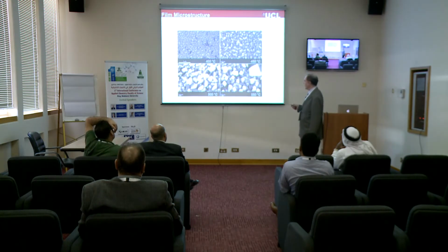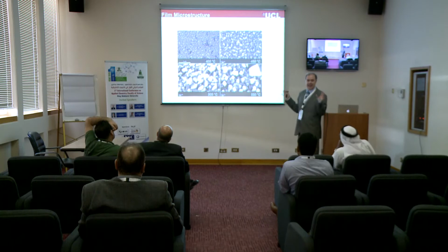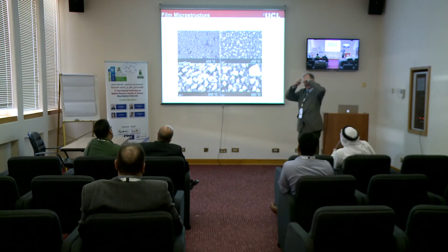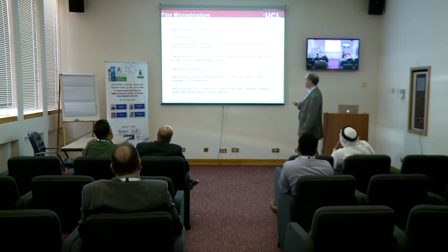When we do that, we produce very nicely crystalline doped tin dioxide films, and this is called a texture coefficient, which gives rise to how much preferred orientation you have in the film. When you look top down, this is what they look like. And they have this pyramidal microstructure. Now that's absolutely ideal for solar cell applications because you want to scatter the light into the solar cell. And these films are used for solar cells very, very widely.